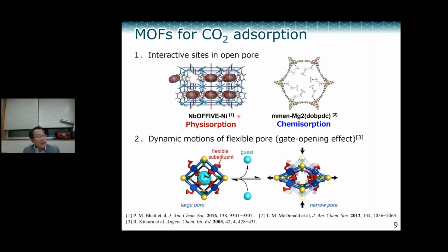And another type is the so-called gate opening framework. In the gate opening framework case, before and after gas encapsulation, the framework shows a very big distortion like this. That means you can expect a big volume change before and after gas encapsulation. So far, these three types are the more well known.